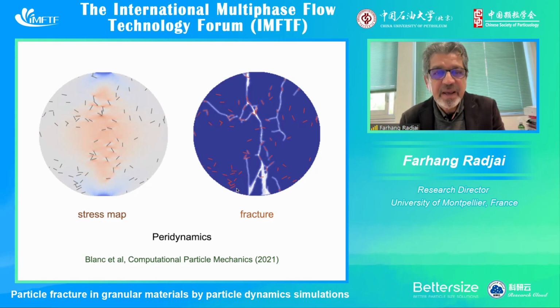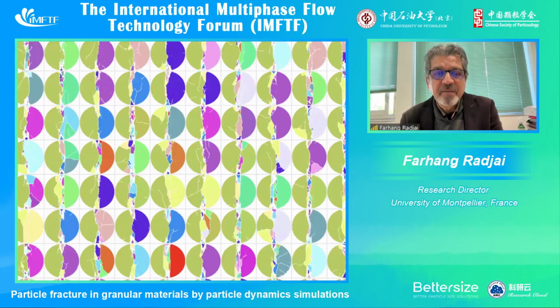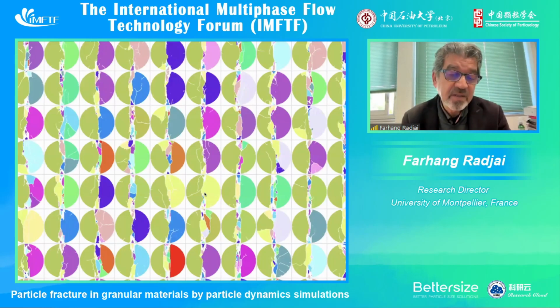And as you can see, by using this continuum approach, which is rather fast as compared to FEM or other methods, we can get the crack propagation and the fracture surfaces inside the material. This has been applied, for example, to study the effect of the distribution of disorder, the defects, the pre-cracks inside the material, doing a large number of simulations and then doing statistics. For example, we can measure the threshold of breaking, the tensile strength of the particle, and see how it is distributed.